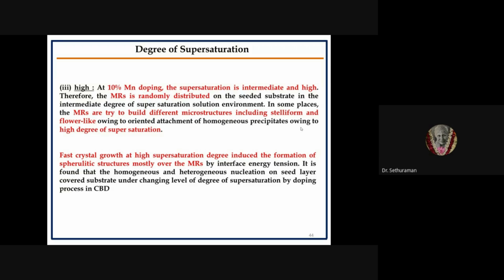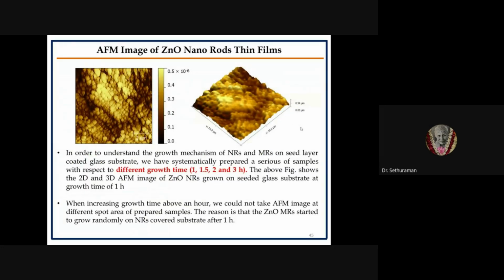So when we increase it further, we get different types of micro rod assembly. So for the nano micro rod assembly on one substrate, we also get nanorods on the surface of the nanorod micro rod assembly by simply doping Mn, and we found that the change in the degree of supersaturation plays an important role in the growth of the nano micro rod assemblies.